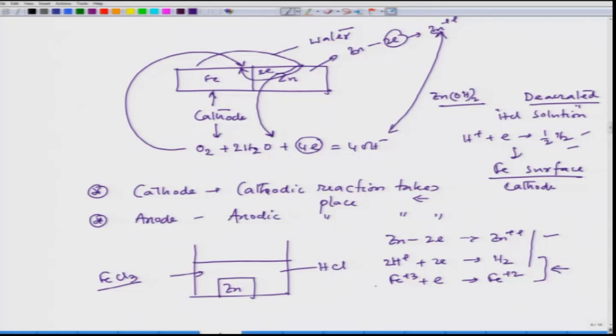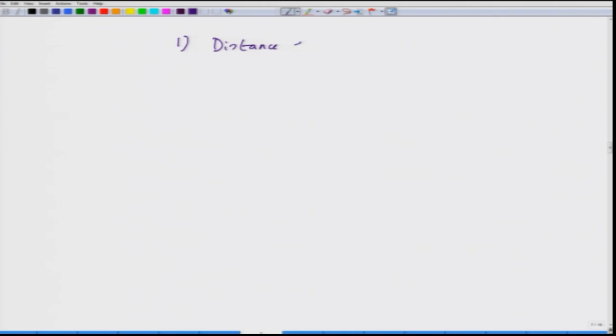This gives an example that metal ions can also be reduced provided the solution contains those metal ions. If this system is dipped in HCl solution containing a little FeCl₃ contamination, that Fe³⁺ reduction reaction also takes place and zinc dissolution increases in that couple. This is galvanic corrosion, and in galvanic corrosion there are important factors — one of which is the distance effect.